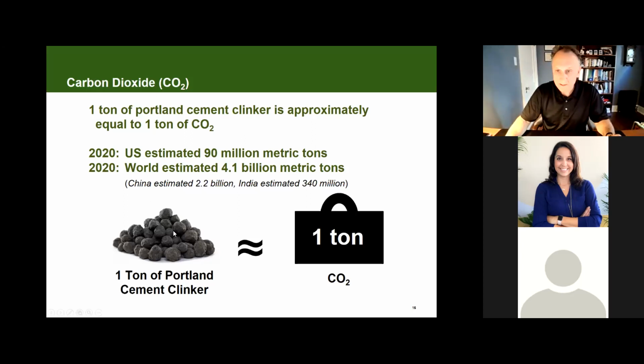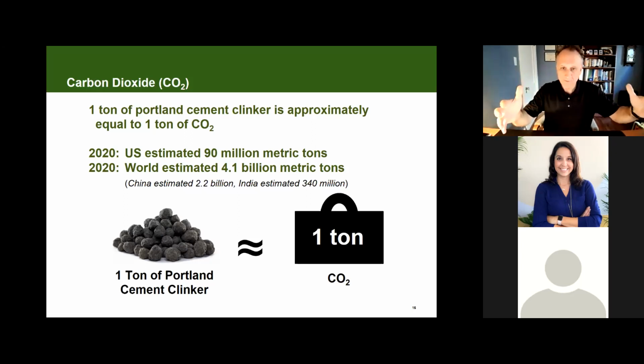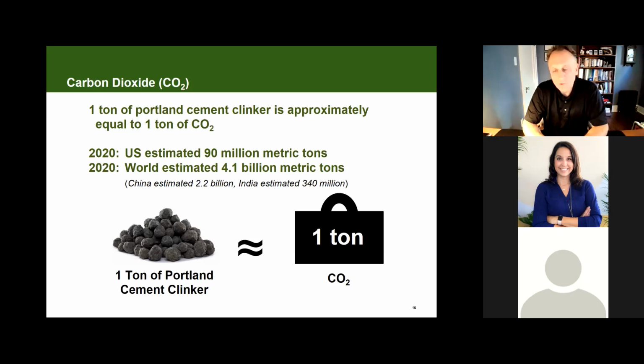So if you follow me there, here's our 1 ton of Portland cement clinker. Let's say we took 5% of that clinker out and only made 95% clinker, and then put, say, 5% ground limestone into that 1 ton. So let's say we marketed to the concrete producer a product that is still 1 ton of cement, but it's 95% clinker, 5% ground limestone, and he makes his concrete. What did we just do? Well, we've saved 5% of the CO2 at that plant.